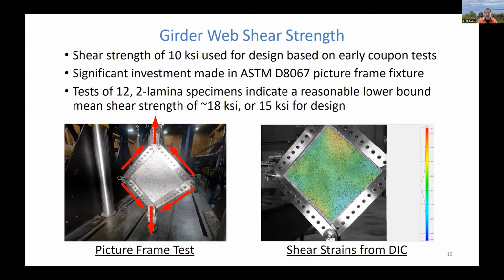And you can see from the picture on the lower right, we monitored shear strains during the test using digital image correlation, and we got a very uniform strain field in there. Those are the shear strains DIC predicts, and you see from the colors that it's pretty uniform shear strains, especially as we get towards the middle of the specimen. And we ran 12 tests of 2 lamina specimens. So these had 2 E-glass FRP lamina on each face of that foam core web. And those tests gave us a reasonable lower bound mean shear strength of about 18 KSI.